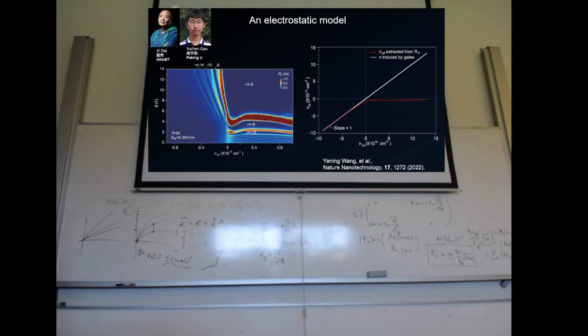Conventionally, n total should follow the white solid line because it's a capacitance coupling from the gate, right? It has to smoothly go from the hole side to the electron side without any interruptions. But along this line cut at D effective equal to 0.35 volt per nanometer, everything follows the white solid line at the beginning, but then departs from some point and goes to a negative value everywhere. So that means all the electrons that should be injected from the gate into the graphene didn't go into the graphene. The graphene stays in a hole-doped state.